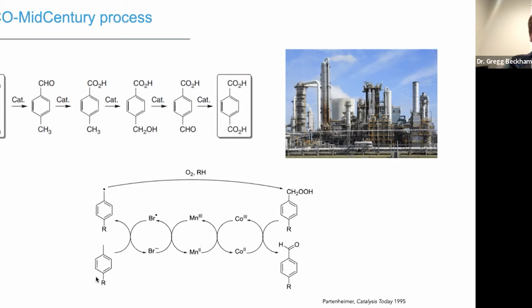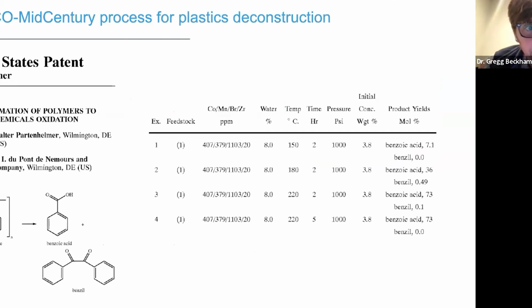And the way that this works is you have some hydrocarbon substrate, in the case of paraxylene or xylene or toluene, and there are multiple steps that occur. This process uses bromine for a radical initiator, and so bromine removes an electron and initiates this reaction, thereby activating oxygen with this radical. And cobalt and manganese are essentially metal promoters that are able to promote beta fission reactions and oxidation, further auto-oxidation reactions through this process.